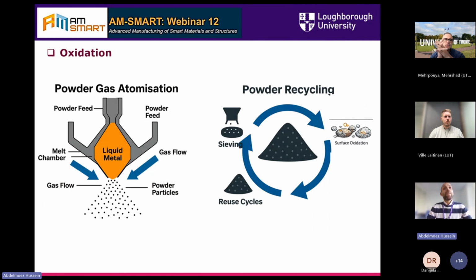The second one is oxidation. What's the amount of oxides in this powder? This can be determined during the atomization process. A lot of powder you can just start atomizing without gas to protect from oxygen. However, magnetic materials are very, very sensitive to oxidation. Even a very small amount can change the material properties.